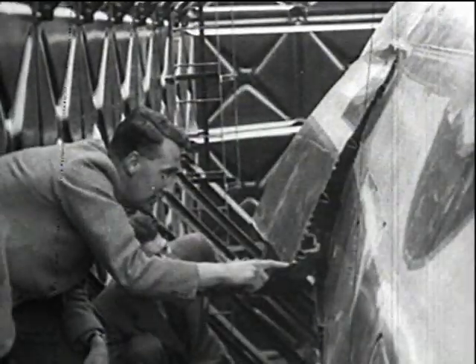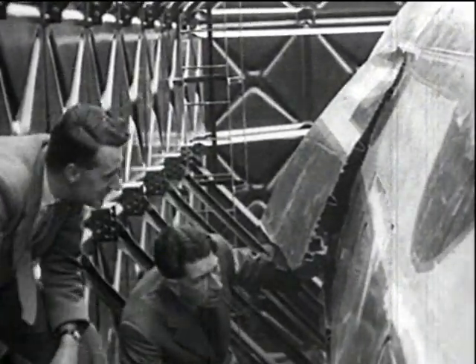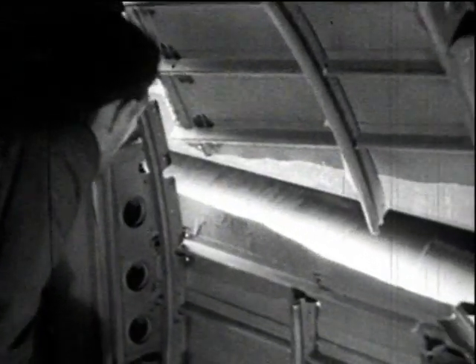When the equivalent total life was about four and a half times that of the Elba Comet, a further failure occurred — a crack near a window developing rapidly, and the port side of the cabin was ripped open for a length of about 15 feet. This third failure confirmed that the structure around escape hatches and windows was vulnerable from the fatigue aspect.